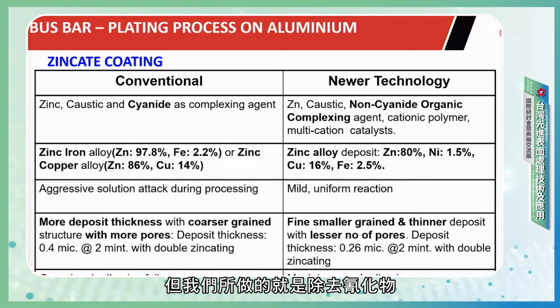But what we have done here is remove cyanide from the usage. Instead of cyanide, we have used non-cyanide organic complexing agents, mainly dicarboxylic acid, or acids with more carbon atoms, so let's say quadra or hexacarboxylic acids, along with some cationic polymer and multication species.